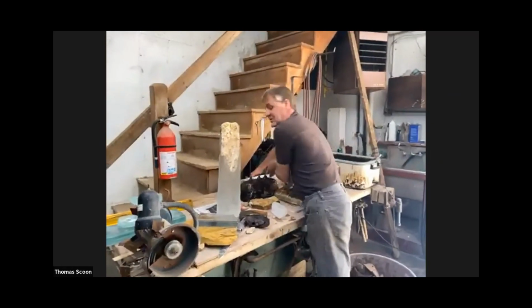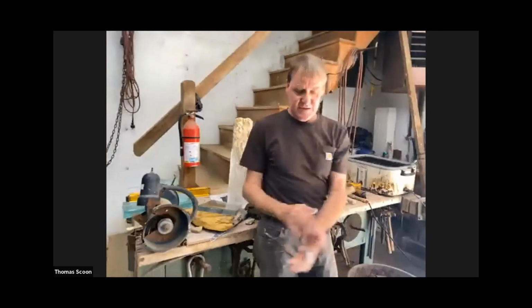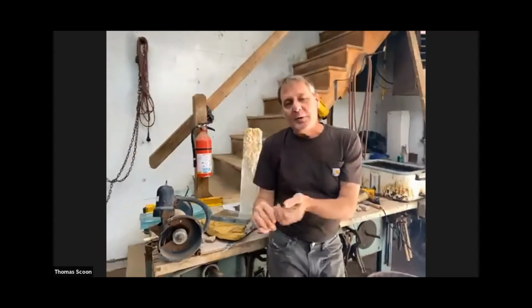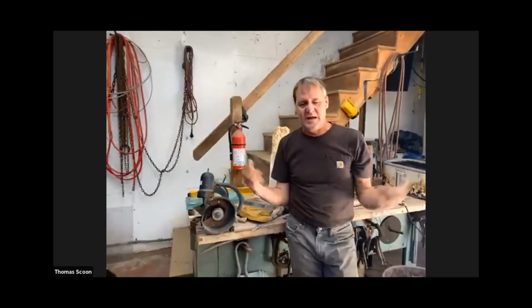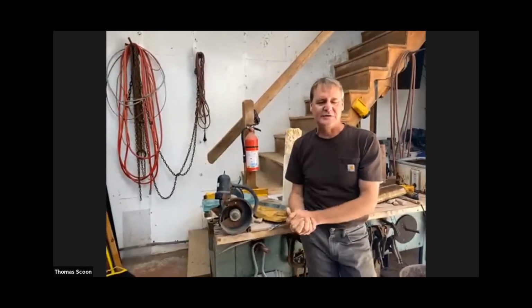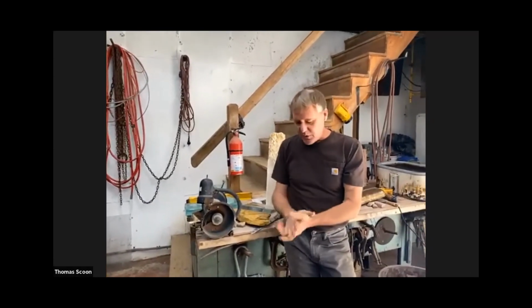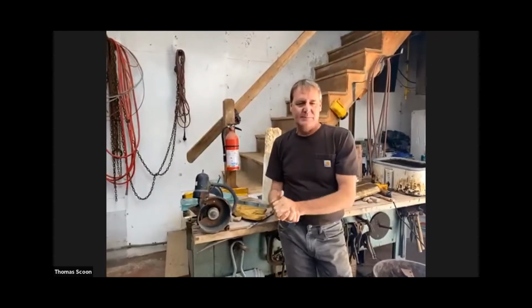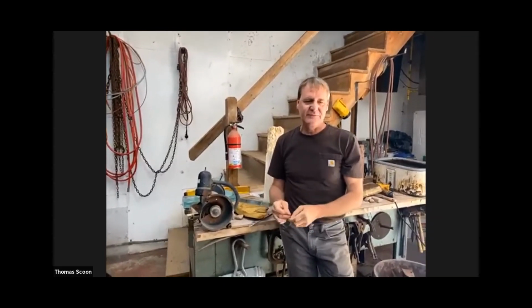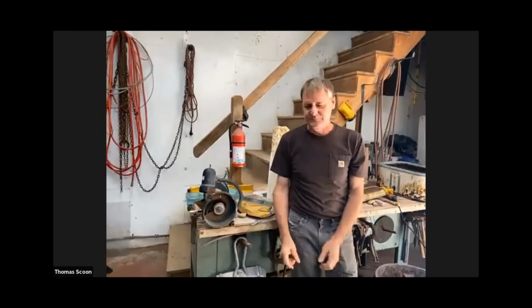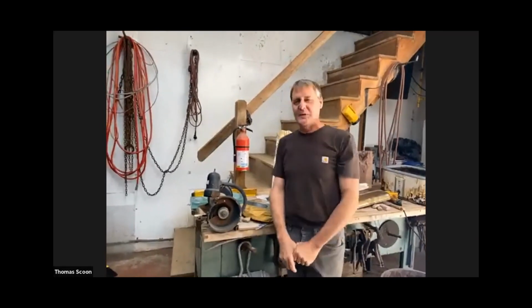Or you can have a large scale piece in the kiln for the month. You open it up, there's a crack running through it, and basically you throw it all away and start all over. Does that happen often? No, but it does happen. At this point in life, there's probably 10% loss, but when that happens, that's a bad day.